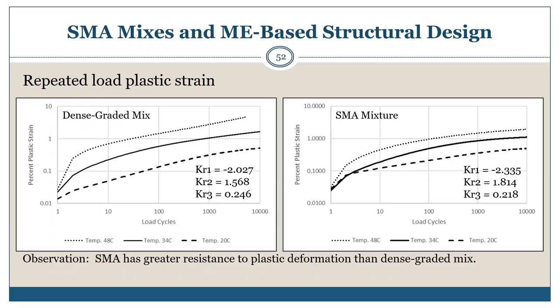The lower KR1 value, or the larger the negative value from the repeated load plastic strain test, means the more resistance to deformation or rutting in the early life of the wearing surface. The lower KR2 value, the less sensitive the mix is to plastic deformation as a function of temperature. Higher KR2 values generally exhibit higher rut depths, everything being equal, which it is not.